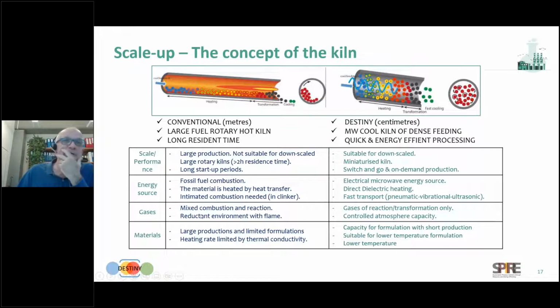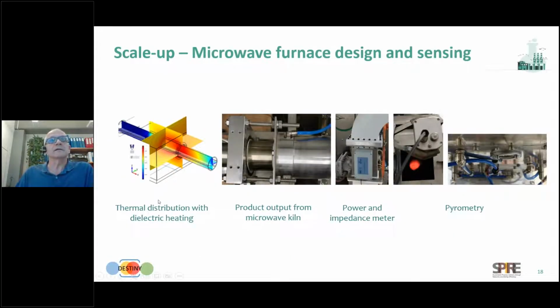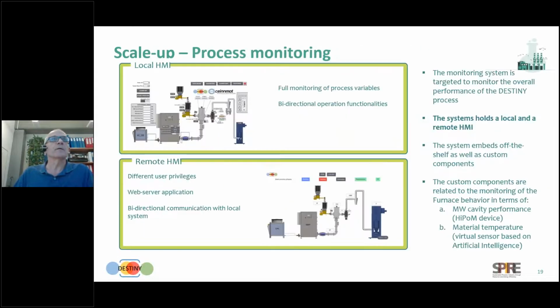Another relevant thing is the gases. In the microwave you can recover the gases because they are only gases of reaction. There is no CO2 contribution, no combustion gases, just the gases of the reaction that you can then use for other things. This is the design, from the simulation to the performance. You can see here a red point because we are working at more than 1000 degrees. But the system is always metal, and it's quite cool, so it is not overheated outside.